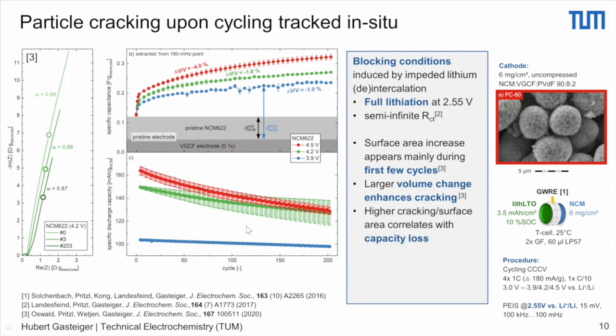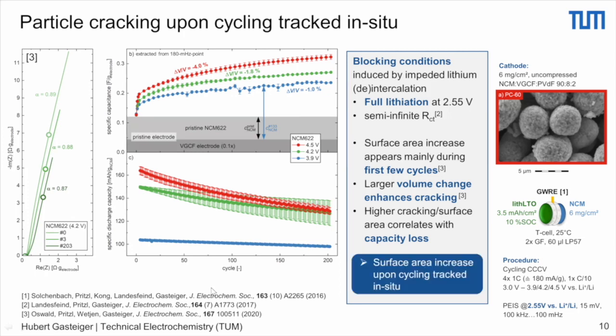And of course, what we see is that at higher potentials, you get more cracking, you expose more surface area, you have more side reactions. And this, we believe, is the reason why when you go to very high potentials, you have more capacity fading, or one of the reasons, than if you cycle at lower potentials, right? So here, the specific capacitance changes by maybe 10, 20%. So this is, of course, well known. And so the other effect we wanted to look at is, what is the effect of oxygen release from the surface upon the surface area increase of the material?